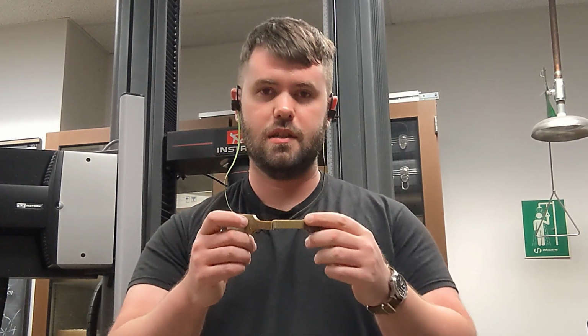Okay, that is the Polymers lab. So we have seen the effect of strain rate and polymer crystallinity when comparing LDPE and HDPE. We have seen the effect of cross-linking, comparing a heavily cross-linked epoxy to a very lightly cross-linked elastomer, both of which though experience brittle fracture and little to zero plastic deformation, but our elastomer had quite a lot of elastic deformation. So that's the lab.